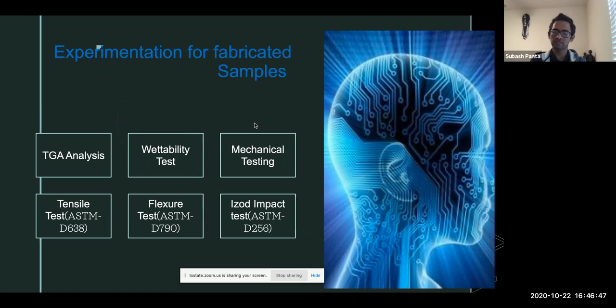D256 were conducted. TGA analysis is done to ensure that the aluminum nanofiber is properly silanized with dichlorodimethylsilane. And the wettability test is conducted to check the wetting contact angle made by the resin with the substrate.